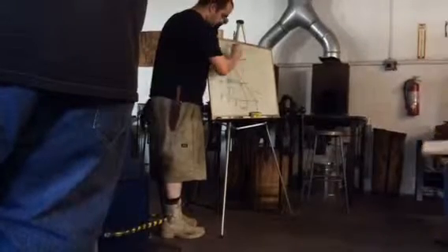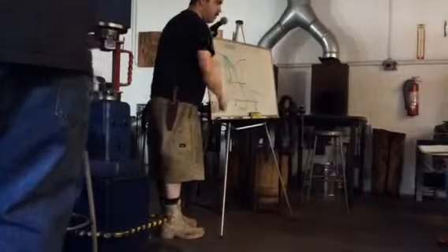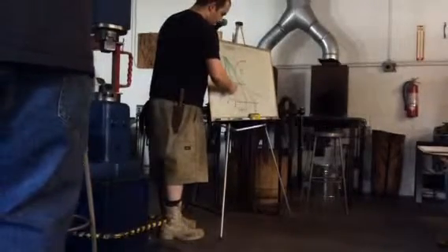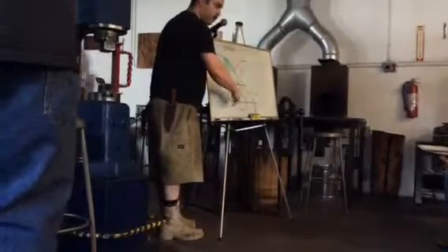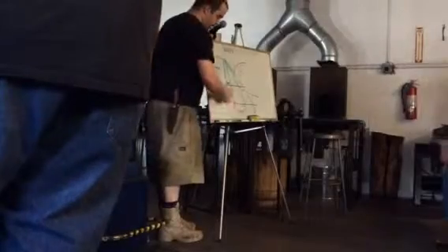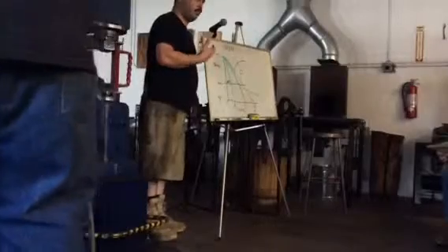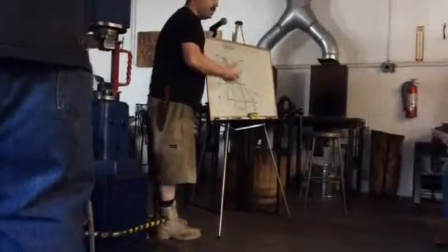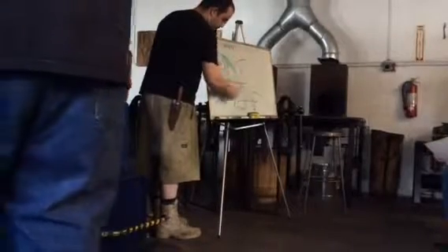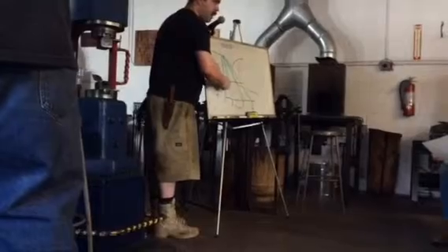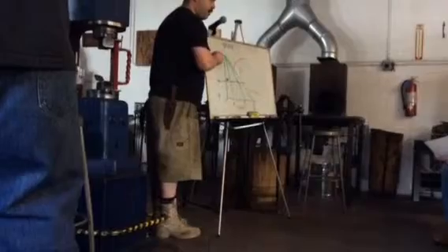So it brings everything down past about 900 right at the tip of the nose, and then into this 400 and lower. Why is 400 important? Of course, it's obvious why this cooling curve is important, because we want to stay out of that pearlite nose. So why is 400 important? 400 gives you a very magical point in the blade's heat treating, a grace period in which you can straighten any warps. If you cool down past 900, get past that nose, and get to 400 and pull it out, it's in a state of austenite, which is the excited non-magnetic form of steel.